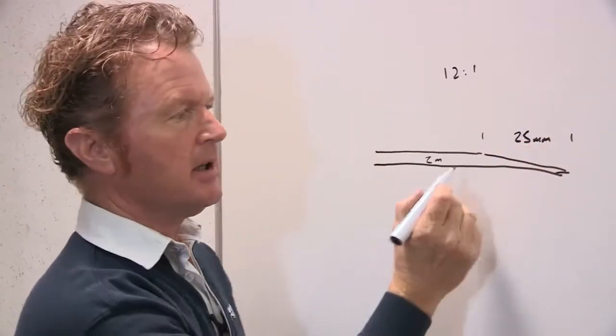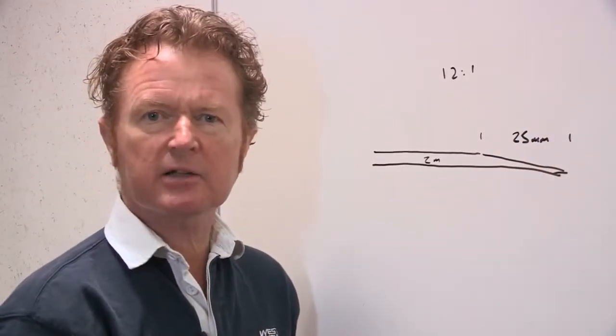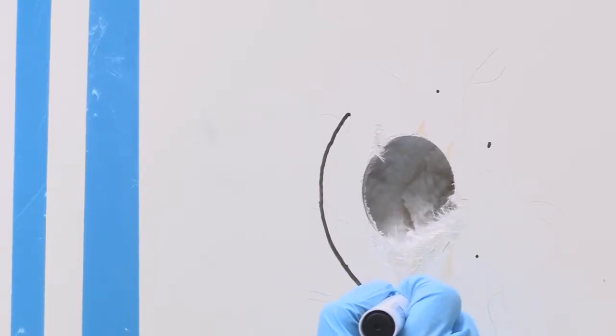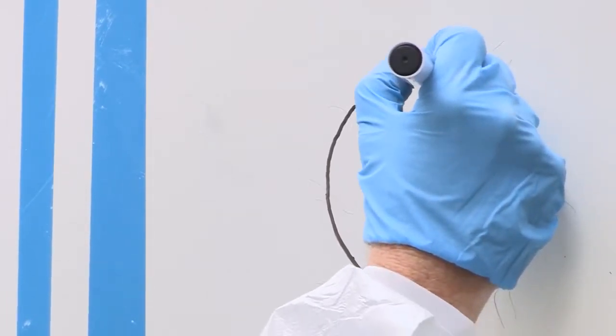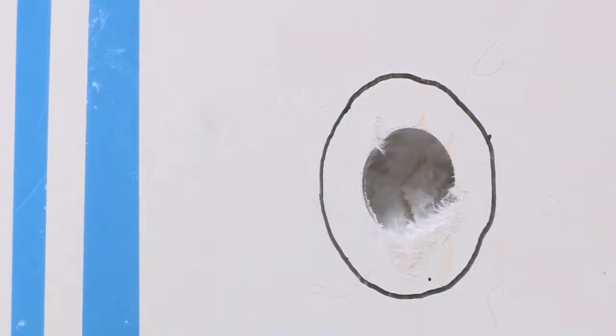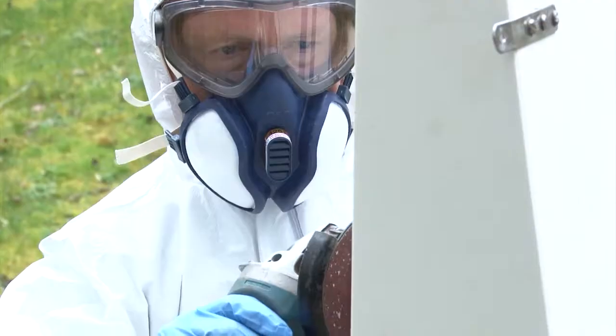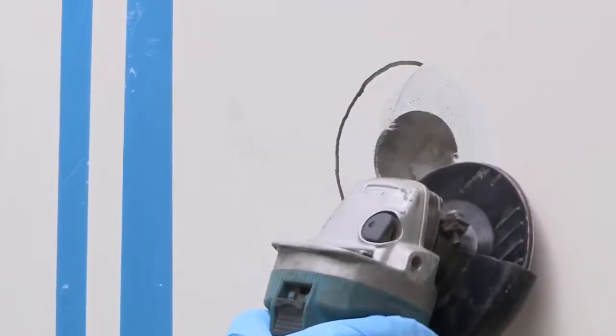We need to grind this with an angle grinder. And I already measured the thickness of the laminate at 2 mm, so my bevel needs to be approximately 25 mm. I'm using a disc grinder with a flexible sanding disc with 60 grit to create my 12:1 bevel.